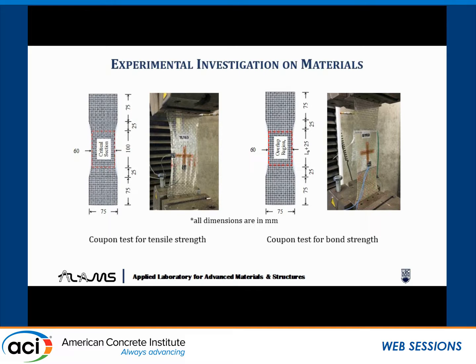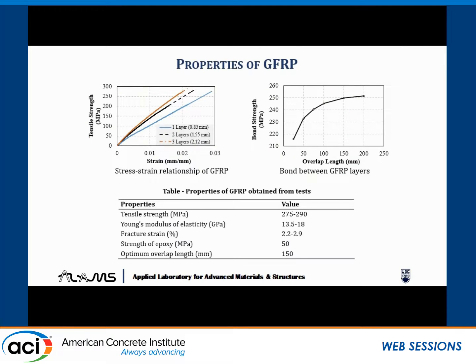So we tested various coupons. When you are doing the confinement for regular GFRP or other CFRP, there is a particular overlap length that you have to provide. So we tried different overlaps to see how much strength can be achieved, whether we can achieve the full strength with larger overlap. We also tested different layers of GFRP: 1 layer, 2 layers, and 3 layers. This is showing the overlap length, and we see that after 150 millimeter, it flattens out. So 150 millimeter you can consider as an optimum overlap length.